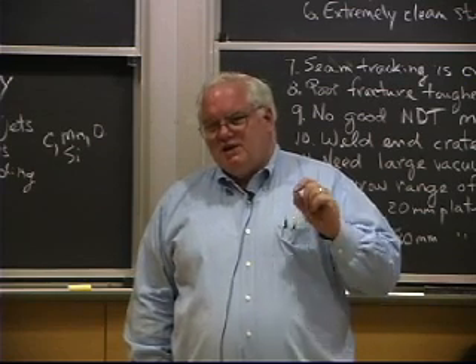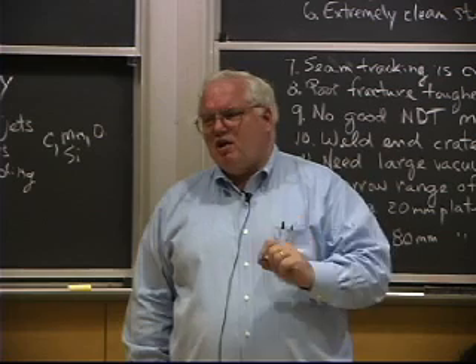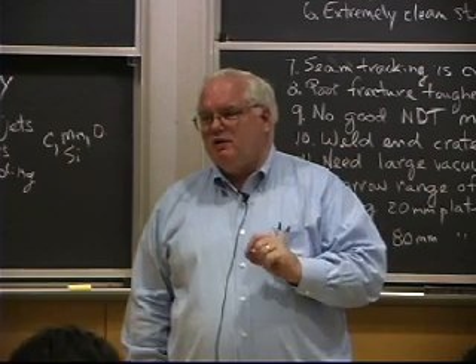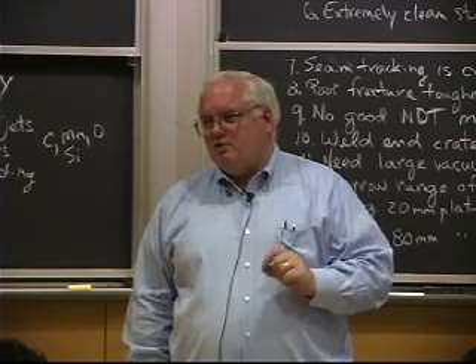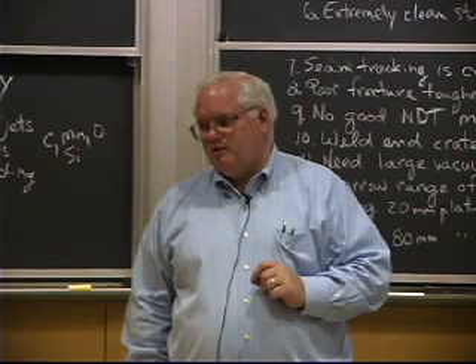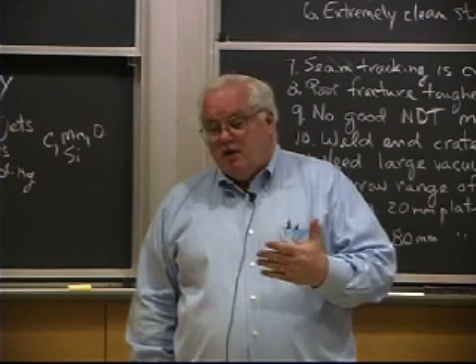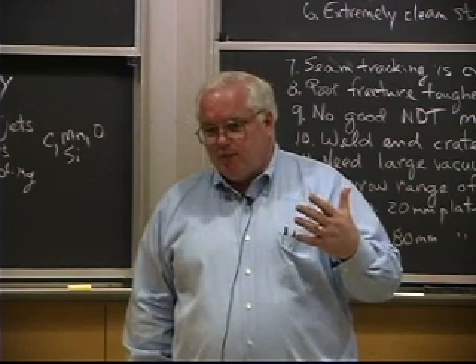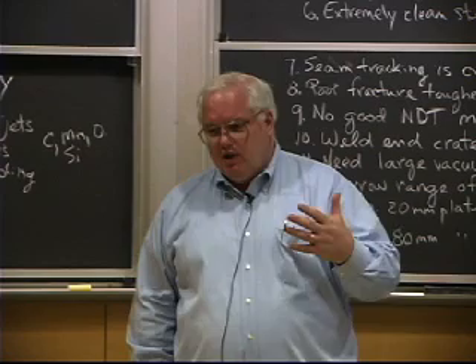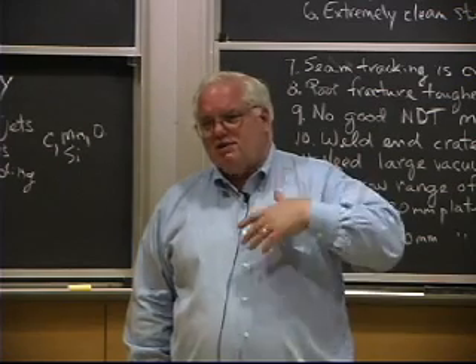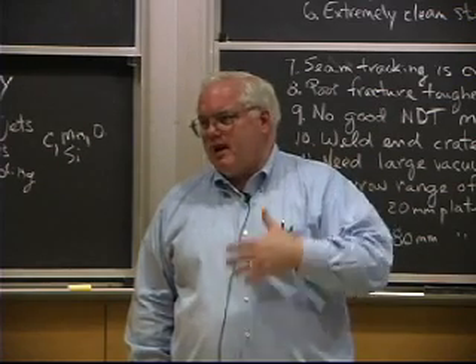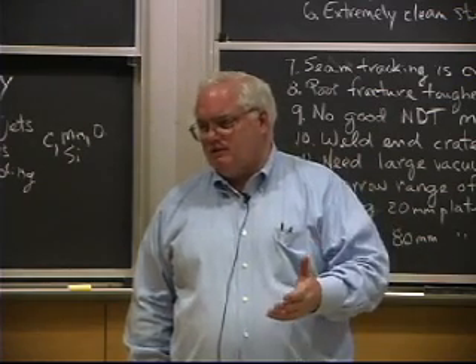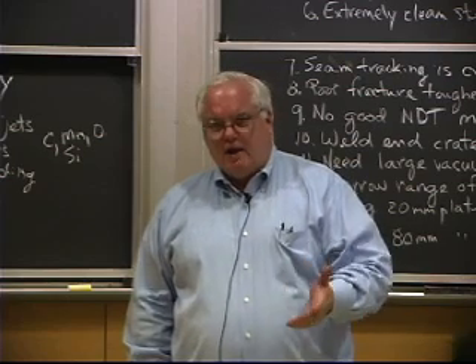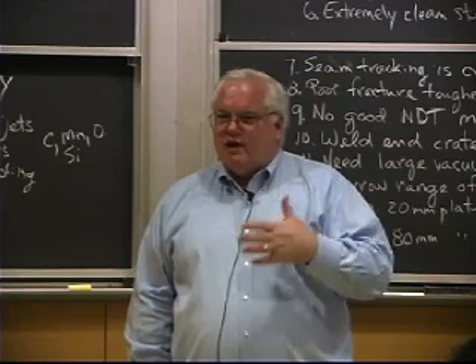It was because they used a 100% CO2 welding wire, and they probably used argon shielding as the shielding gas. Ordinarily, you have to have wires with like 2.5% manganese and 1% silicon with 100% CO2 because the 100% CO2 is going to burn off a lot of manganese and silicon during the welding process. You're going to lose those alloying elements. So you have to put extra into the wire,